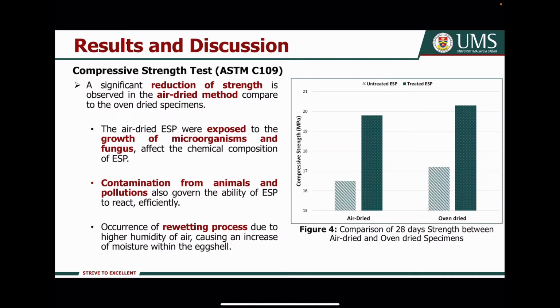On the other hand, there is a significant reduction of strength for the air-dried method compared to the oven-dried method because the air-dried ESP is exposed to the growth of microorganisms and fungus which affect the chemical composition. Also, the contamination from animals and pollution govern the ability of ESP to react efficiently, and there are also occurrences of a rewetting process which increases the moisture within the eggshell powder.